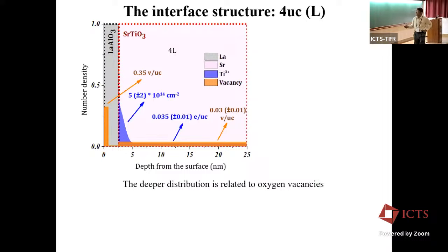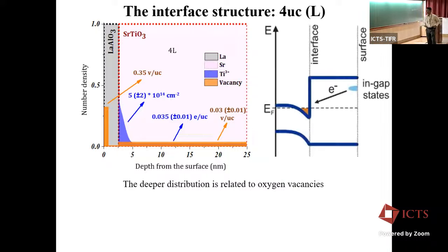The surprise was that, again, it needed two different distributions, but this time the distribution was of the oxygen vacancy. There was one that was distributed throughout strontium titanate, which is presumably responsible for this entire part of doping of the strontium titanate, but the other oxygen vacancy was not tied to the interface, but was tied to the top layer of lanthanum aluminate. It looked like the lanthanum aluminate lost some oxygen. Essentially, every oxygen that went away from there donated 2 electrons, and that is what came over here and doped this.